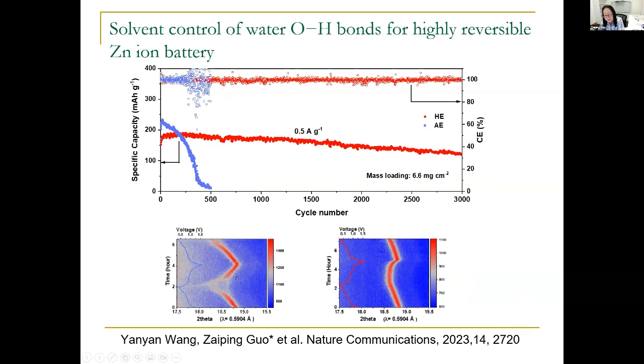And from the in situ synchrotron powder diffraction analysis, we found that in the baseline electrolyte the peak shifts to a lower angle significantly, but in the hybrid electrolyte, the peak shift is much smaller, indicating the strain, the structure change, is smaller. This is possibly because in the hybrid electrolyte, less water is solvated with the zinc ion. So therefore, the structure change is smaller during charge discharge. The structure stability is better for the cathode material.